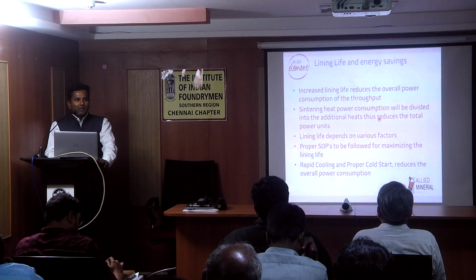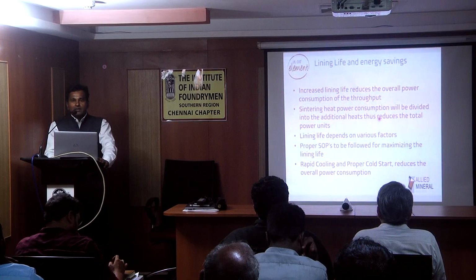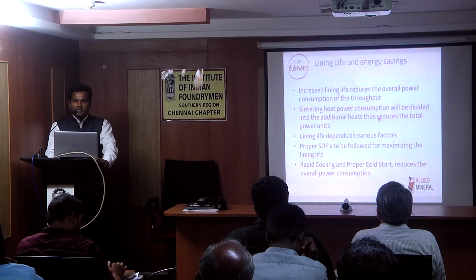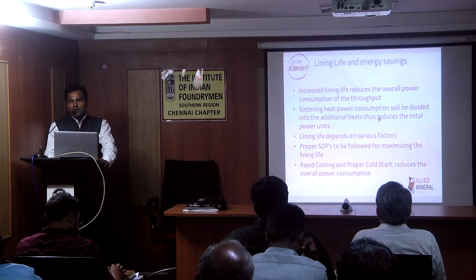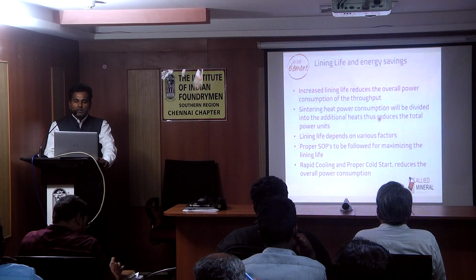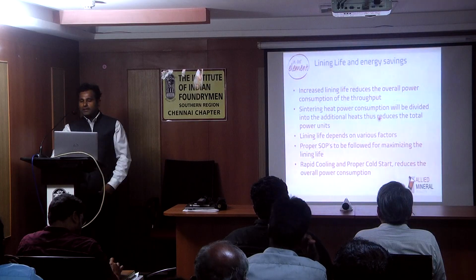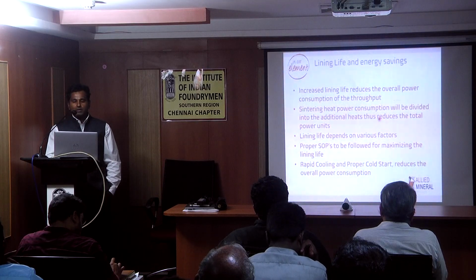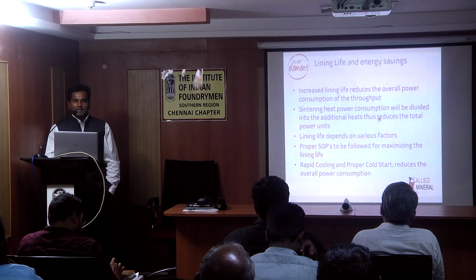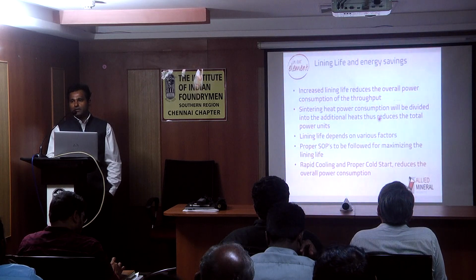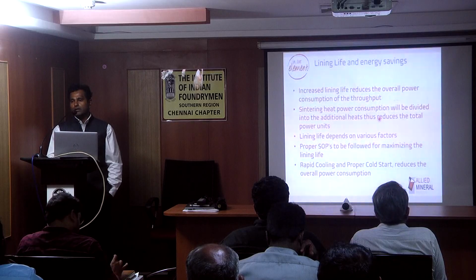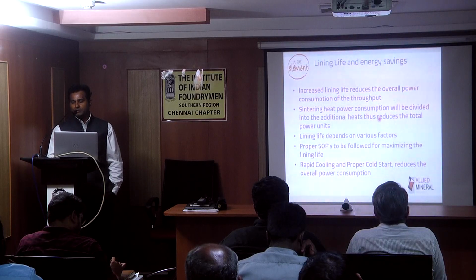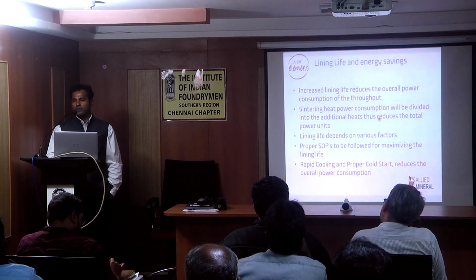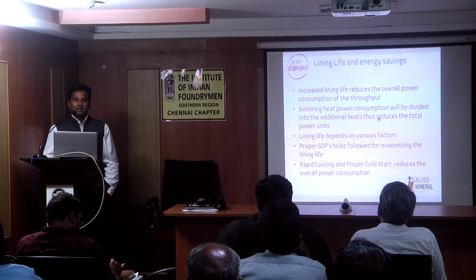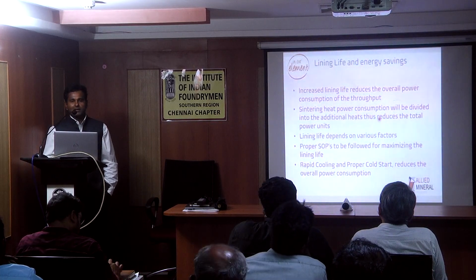So what is the relevance of lining life and energy saving? As Anand sir has explained, optimum lining thickness always gives you better energy saving. Increased lining life reduces the overall power consumption per throughput. As I said, a sintering heat consumes three times the power of your regular heats. So if the lining life is prolonged, this additional sintering power is distributed over the extended lining life.